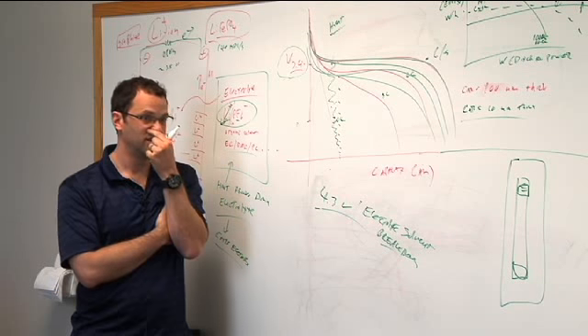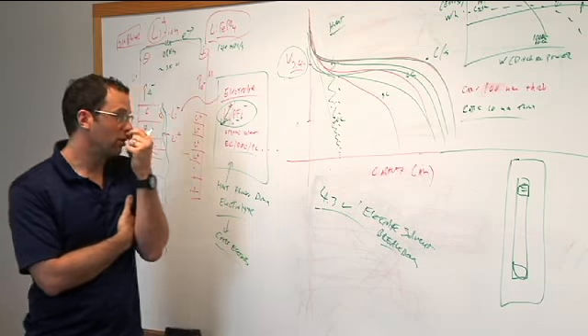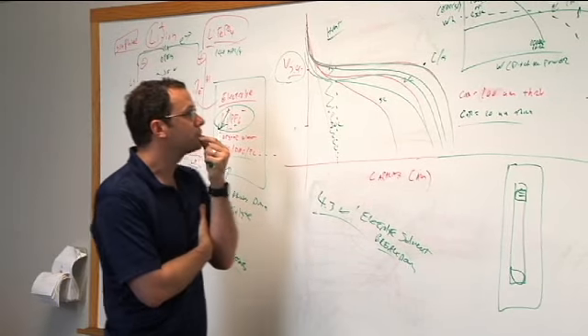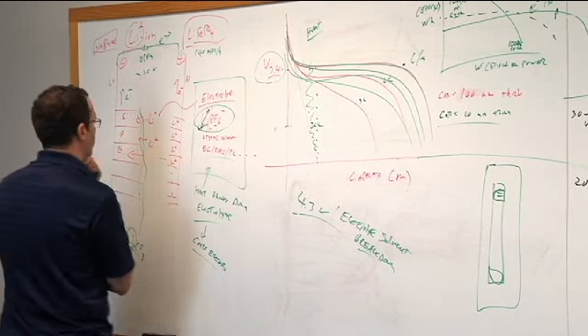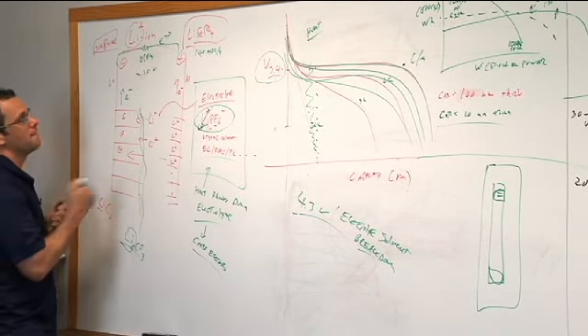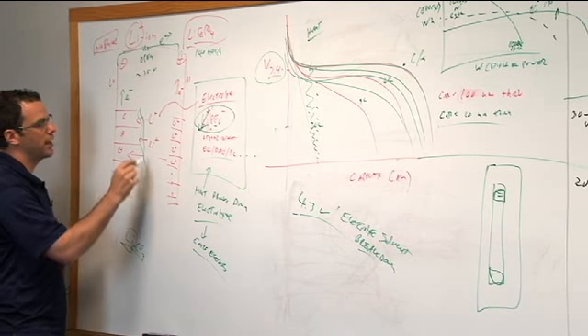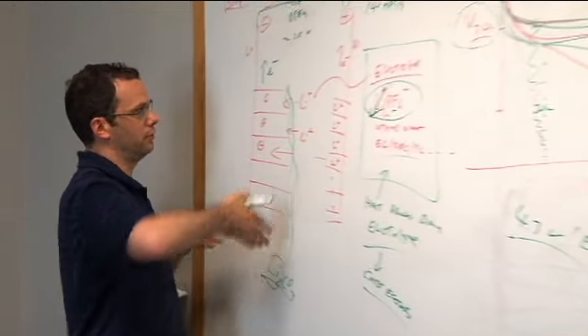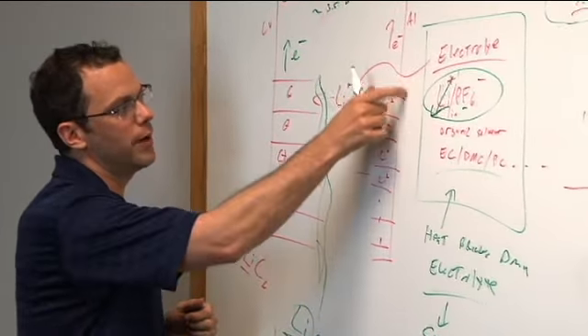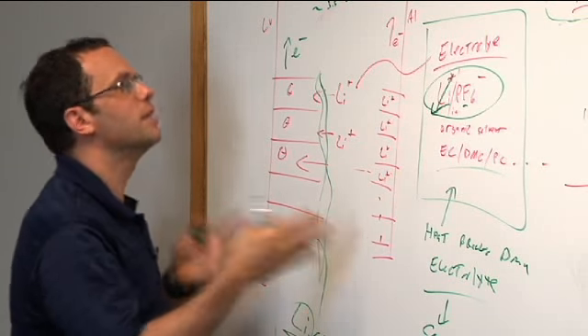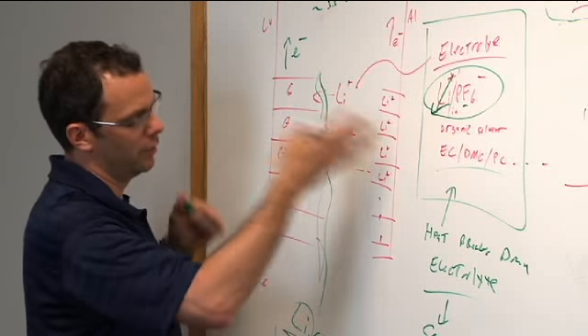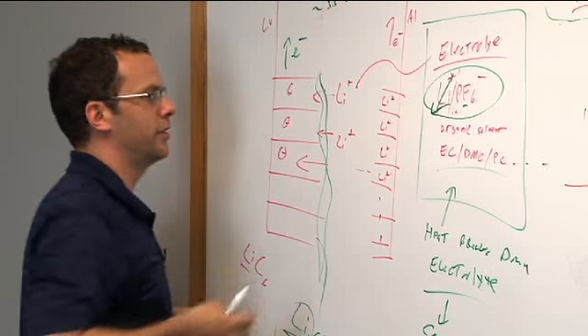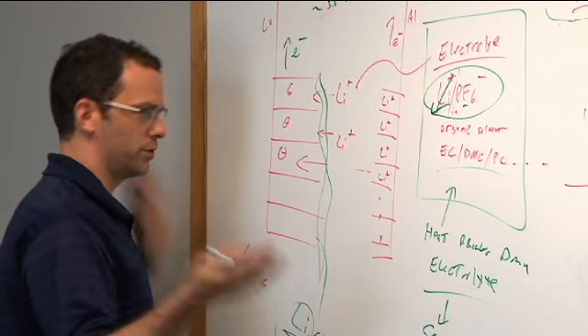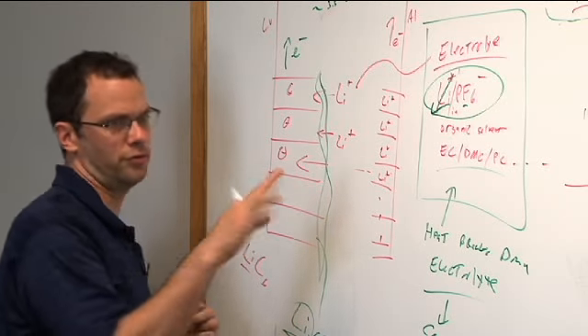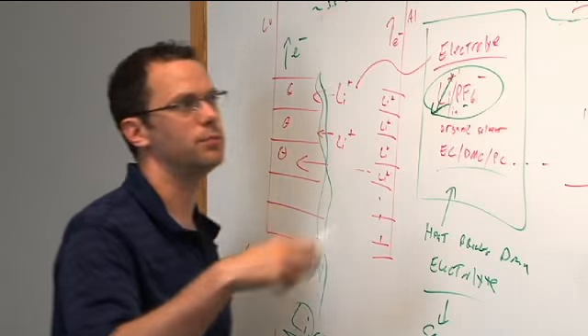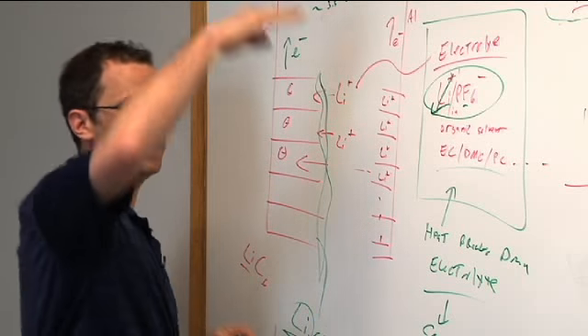Sorry? What's over discharge like? All right, so what happens at over discharge is that you take all the lithium out of the anode. When all the lithium is living in the cathode and there's no lithium at the anode, the natural open circuit voltage is about 1 to 2 volts, depending, and it's quite steep, so a very small amount of lithium change will take you up to 3.4 volts.